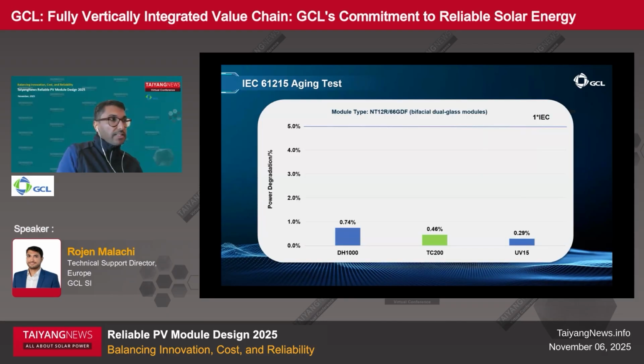So for GCL's NT12R66 GDF, or the golden reference bifacial dual glass modules, we see the standard IEC 61215 aging test results here. This includes the damp heat or DH1000, the TC200, and also UV15 results. So the degradation is much lower than the IEC requirements of 5%.